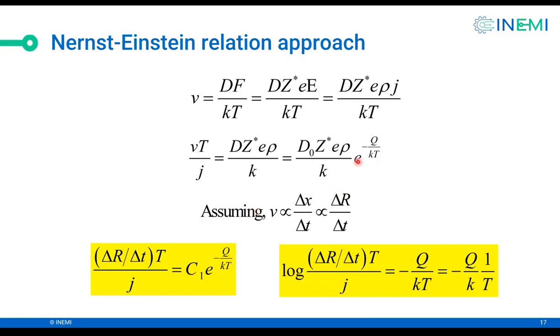So I won't go through the page either, but in this equation, the drift velocity, the velocity of the bismuth atoms, is equal to DF over kT. D is the diffusion coefficient, F is the force on the atom, k is Boltzmann's constant, T is absolute temperature. So we can derive this equation that says drift velocity times temperature divided by the current density is equal to some constant e to the minus q over kT.